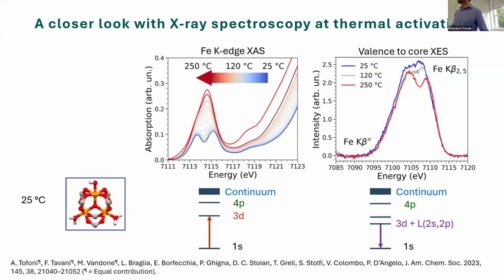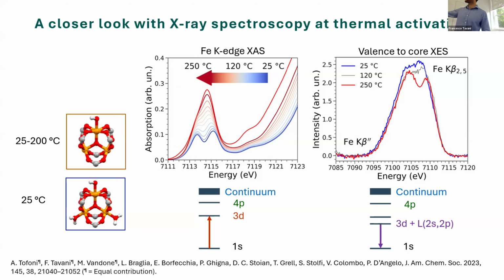Helium, yes. So actually, we ran some simulations, calculations on this, and what we understood is that the pristine MOF, as I mentioned earlier, has two water molecules coordinating these two iron sites in an octahedral geometry, and there's a hydroxyl capping the third iron site in the trimer. Once we reach 200 degrees, we've basically removed most of the two water molecules in the trimeric unit. So two of the three iron sites are five coordinate, and this leads to the increase of this peak.